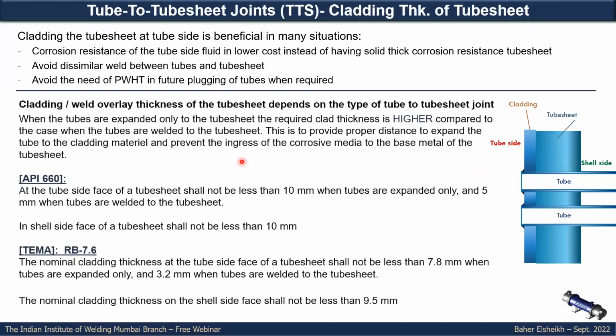We will notice something here for the recommended clad thickness. In case we have only an expanded tube to tube sheet joint, the clad thickness here usually should be higher compared to the requirements in case you have a weld. Why? Because in case you need to do sealing by the expansion, you should have enough sealing distance between the alloy of the tube and the alloyed part cladded here. Otherwise, if it is a small expanded part, you'll have a higher chance of escape of the media to the lower grade material, which might be affected by corrosion.